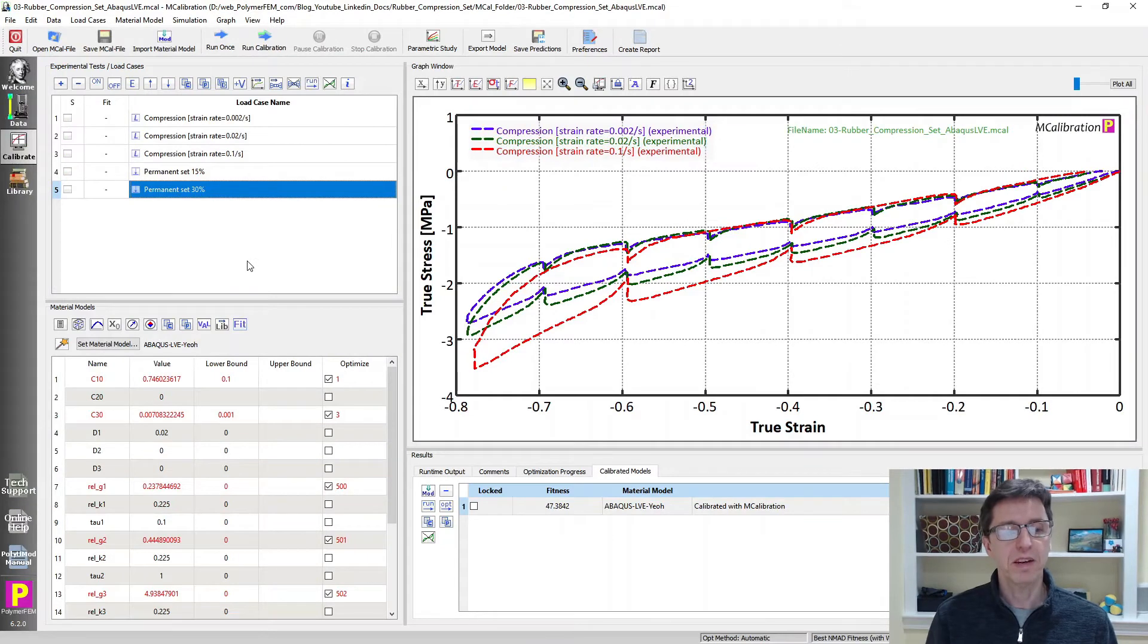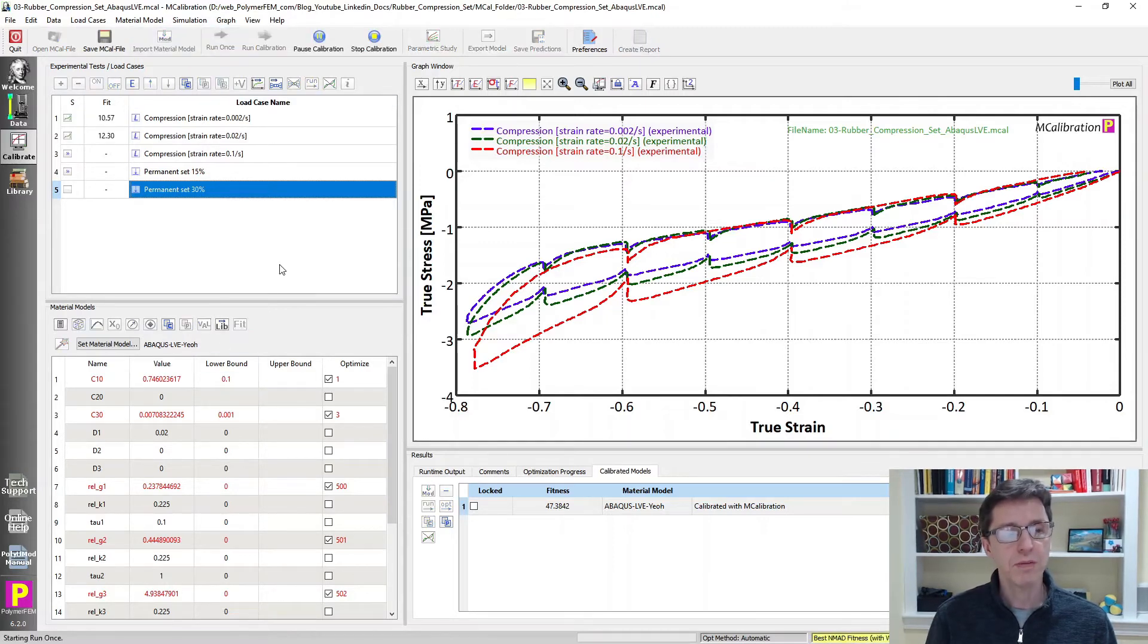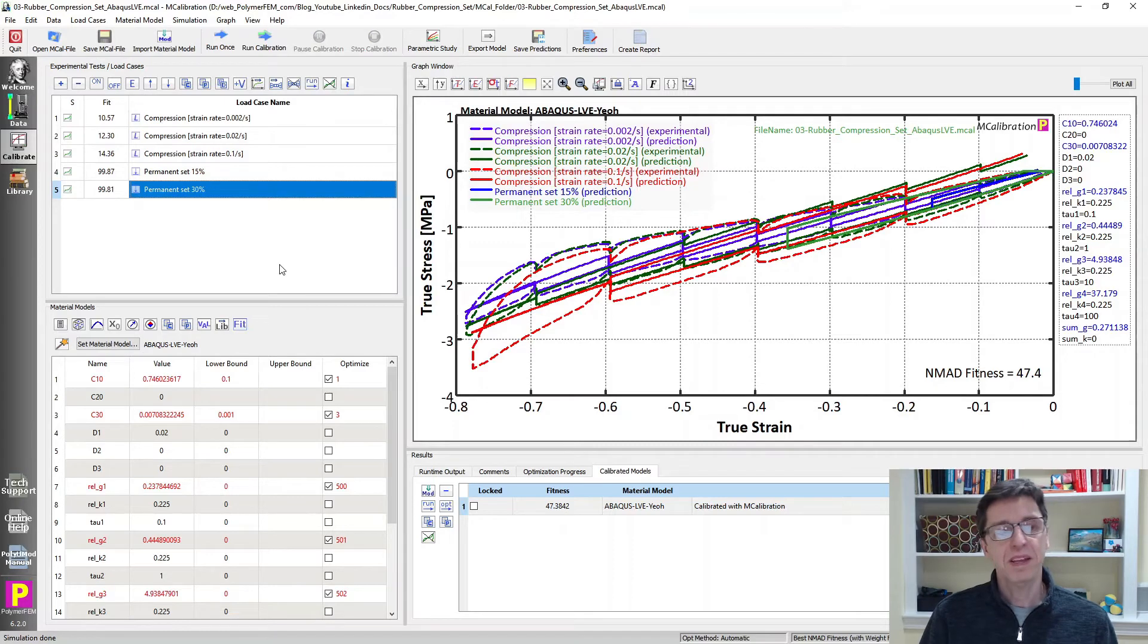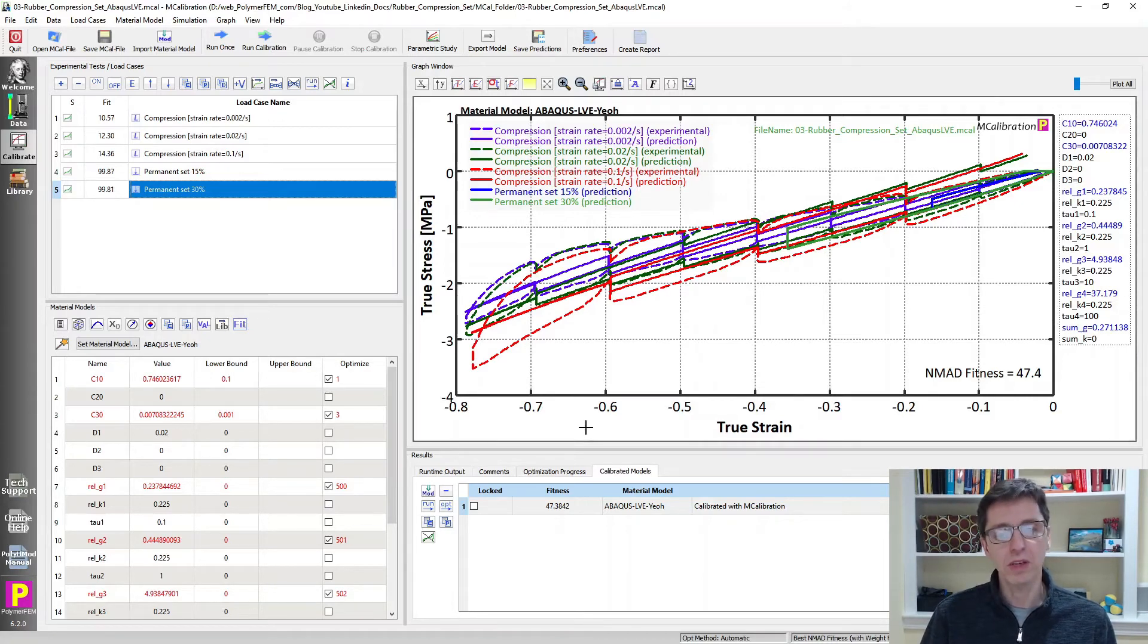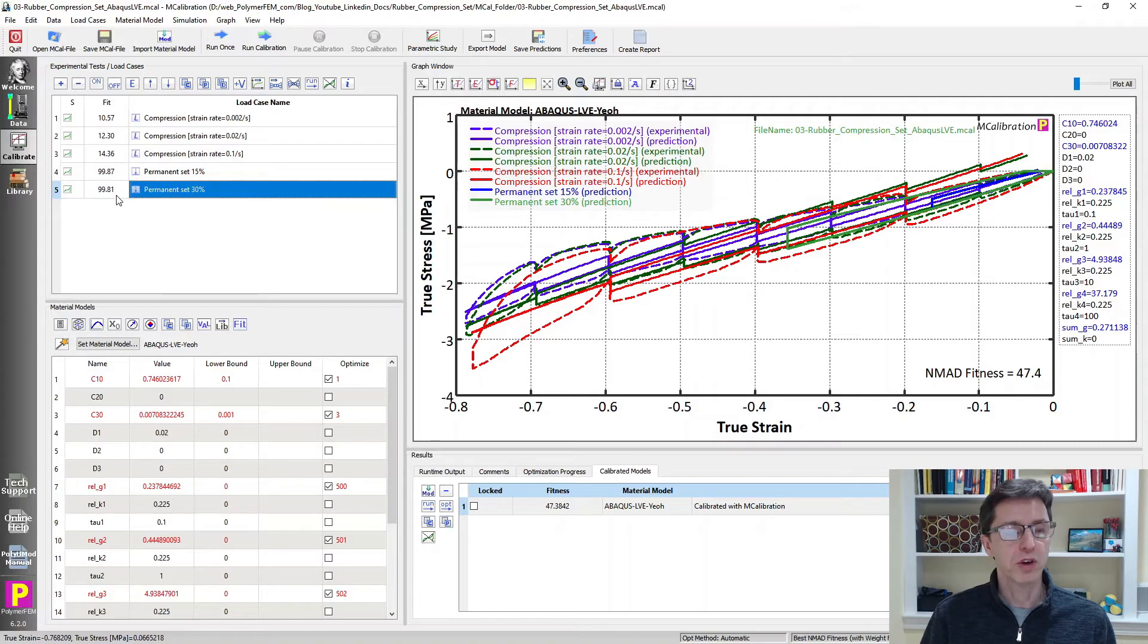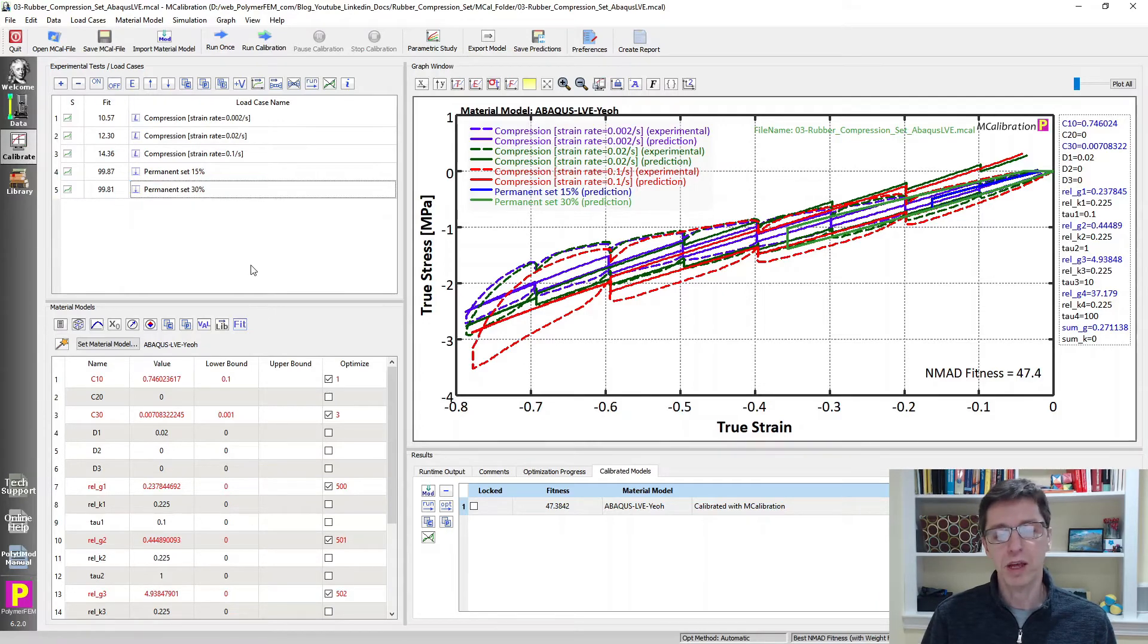What else could we do? Well, how about this? How about a hyperelastic model with linear viscoelasticity? So I looked at that. I calibrated a Yeoh hyperelastic model with a Prony series linear viscoelasticity model. When I run this, I get predictions that are equally bad, unfortunately. That is, you can get a certain amount of slow recovery and therefore potentially a bit of a permanent set with this kind of model. But you can't match both the uniaxial compression data in this case and the permanent set. We get virtually no permanent set whatsoever with linear viscoelasticity. I do not recommend using this kind of model if you want to predict the permanent set of rubber-like materials. Not a good choice.